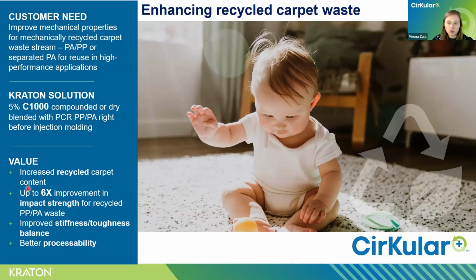So here, because of the material combination, we recommended C1000 as a compatibilizer. Again, it was a low loading level of just 5%. And we compounded it, or it could also be dry blended, with post-consumer recycled polypropylene and nylon right before injection molding.